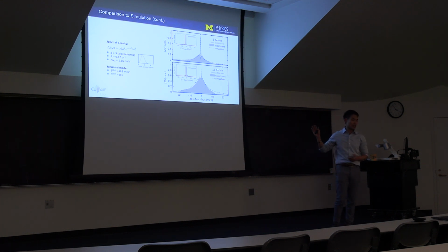It's well known in these nanocrystals that there's fine structure. So the way that you emit light after absorbing a photon is you first non-radiatively relax into a lower lying dark state. So there's an energy gap there as well that contributes to a Stokes shift. And I don't think that makes up the difference. So is the Stokes shift understood in these materials? It's definitely still an active field of research.